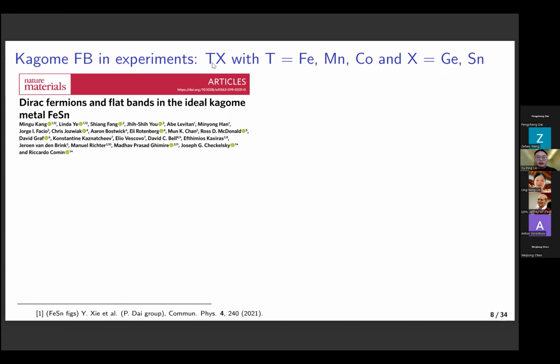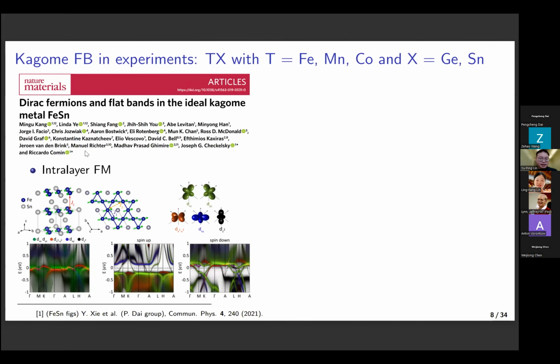So this question has been addressed recently in the kagome flatband compounds. The first family is the binary materials TX, where T could be iron or manganese or cobalt, and X could be germanium or tin. So the first identification of flatband in this family is in the iron tin material. And what are the features in the iron tin materials? The iron tin materials are quasi-2D layer materials. If you look at the structure, you'll see that the iron atoms form a kagome network in each layer. And at high enough temperature, in the non-magnetic phase, the kagome layers have flatbands which are very close to the Fermi level, which is good.